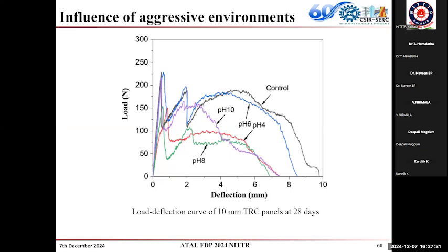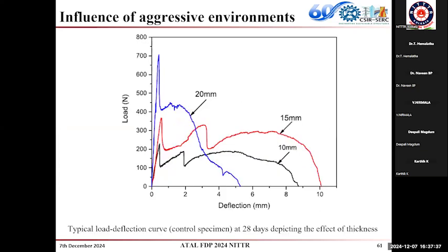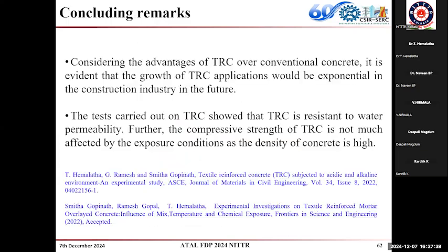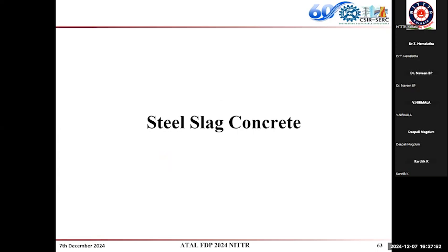So we have subjected it to acidic as well as alkaline conditions, and we have tested for different thicknesses. It showed good resistance to water permeability as well as alkali resistance, and this we have also published. So if you want more details, you can refer to our literature on TRC.